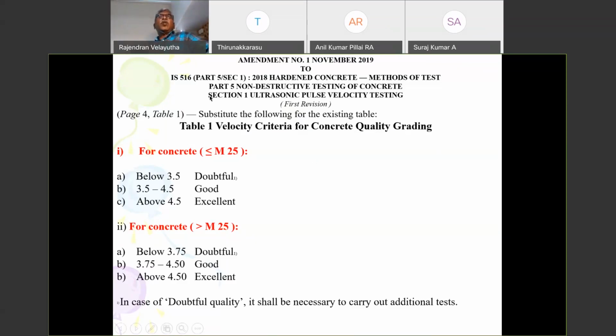But now it has been brought to IS 516 Part 5 Section 1, 2018, where it has been differentiated for two different grades of concrete. Earlier there was no talk about the grade of concrete, whether it is M20 or M50. The guiding values were the same. But today, IS 516 Part 5 Section 1 says, if your concrete grade is less than M25 and your value is less than 3.5 kilometers per second, then the concrete is doubtful. But for M25 and above, if it is less than 3.75, it is doubtful. For example, I get a value of 3.6. If my concrete is less than M25, then it can be inferred the concrete quality is good. But the same concrete, if it is more than M25 and I get 3.6 kilometers per second, it is doubtful and cannot be classified as good.